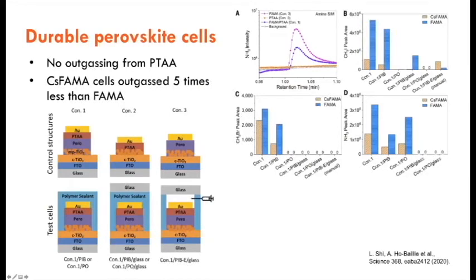We also look at this hole transport layer PTAA. So PTAA is slightly more expensive and a less commonly used hole transport layer. But encouragingly, we found that PTAA doesn't outgas. So at least at 85 degrees, which is the typical operating temperature of solar cells. And we also found that if you have just the encapsulant without the glass, you will see outgassing. So in these second and the third histograms, you can see the outgassing of the signature products. And if you have glass, there's hardly any outgassing.